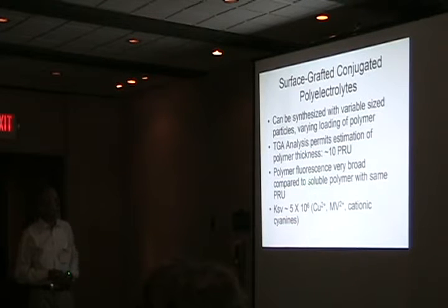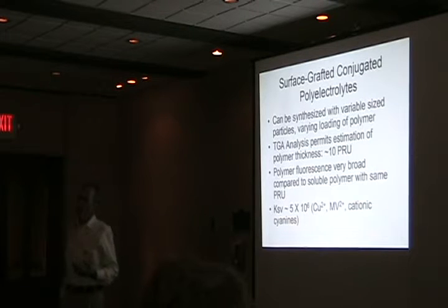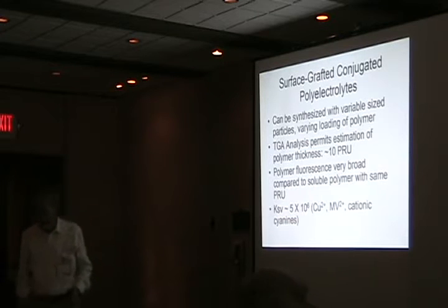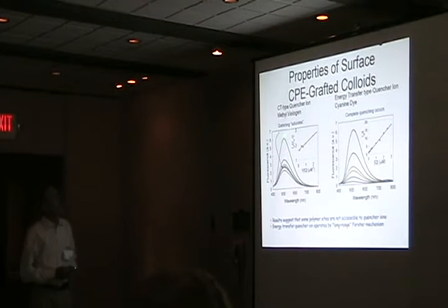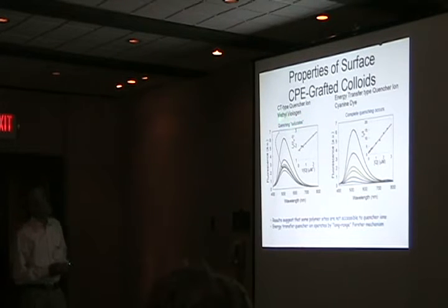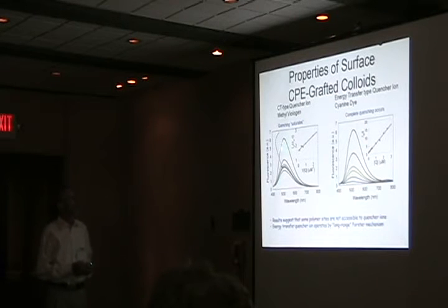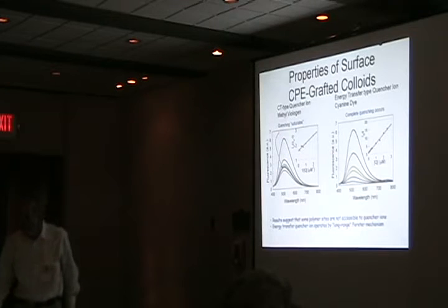We found that the fluorescence can be quenched by both electron transfer quenchers and also by a series of cationic cyanine dyes, which are good energy transfer acceptors for the polymer. But the interesting thing we find is that if we try to quench the fluorescence with, say, methyl viologen, an organic dication that quenches by charge transfer, the quenching saturates. There's about 40% of the fluorescence that can't be quenched at all by this. If we compare that with the cyanine dyes, which are about the same size and relatively similar shape to methyl viologen, we find that for several of these monocationic cyanine dyes, which quench by energy transfer, the fluorescence can be completely quenched. So we are imagining now that there must be many sites where you can't get a quencher close enough to quench.